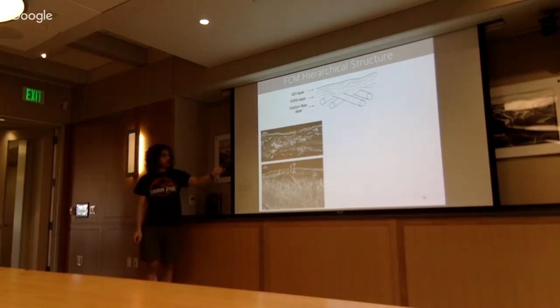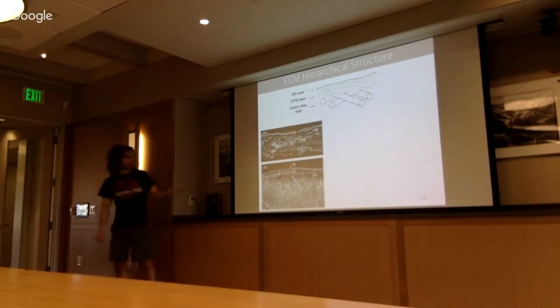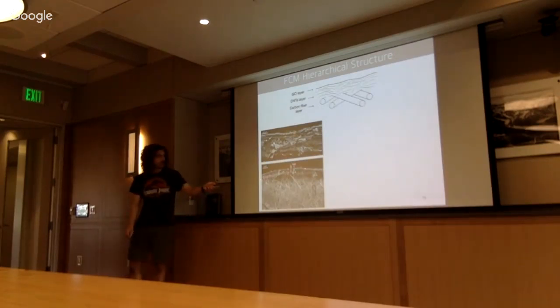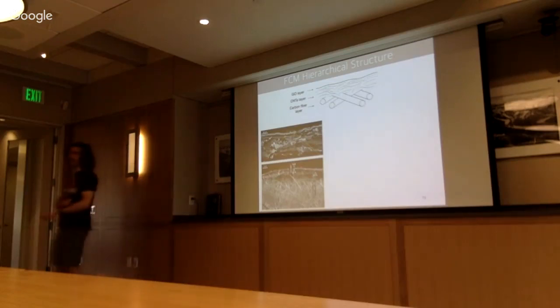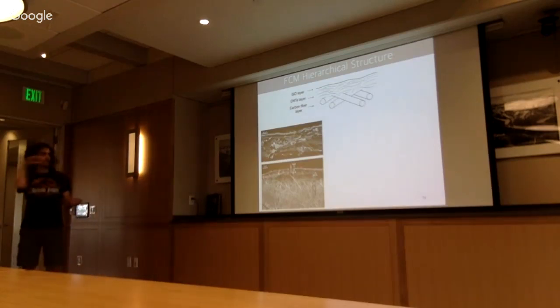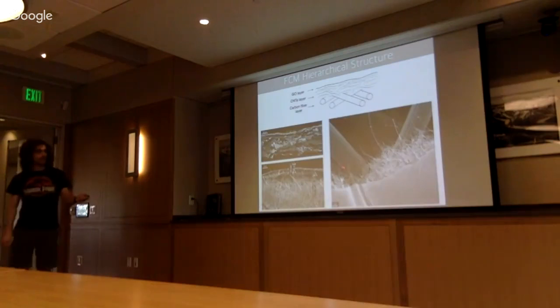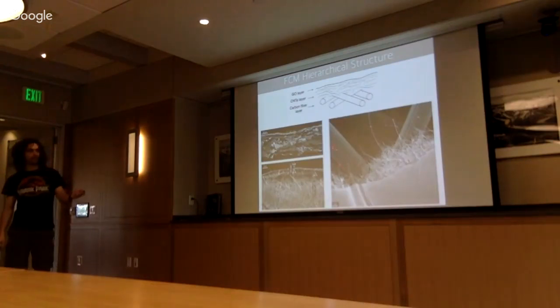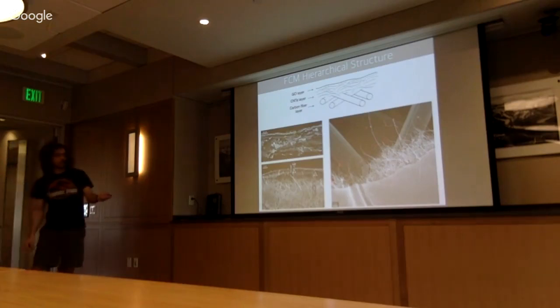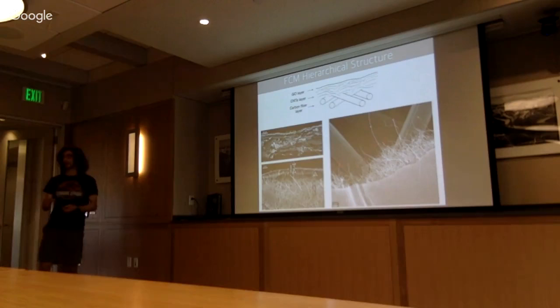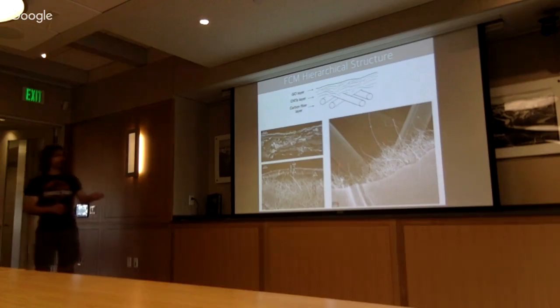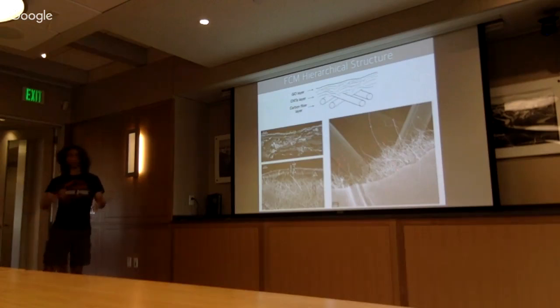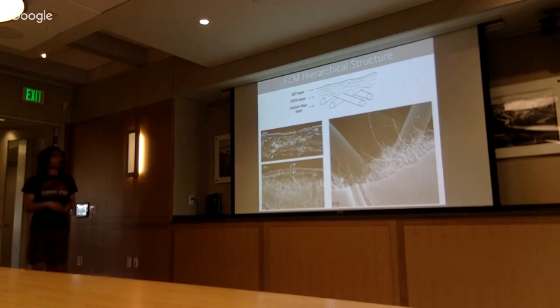But if you're zooming on the top part, we can see the carbon nanotubes layer is about 10 micron, and here you can barely see this really thin graphene oxide layer. If you're seeing a bird's-eye view, we can see a micrometer-size carbon fiber layer, nanometer-size nanotubes, and then the graphene oxide layer on top. So basically, we're creating this hierarchical structure going from micrometer to nanometer to atomic size.